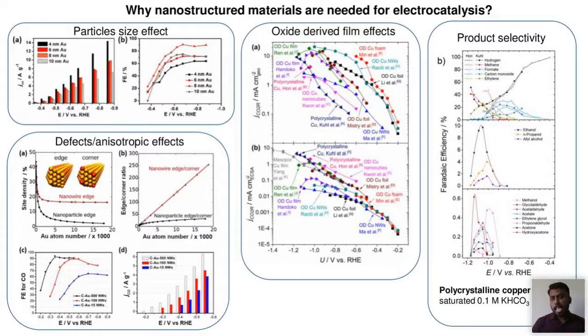So nanomaterial can be any shape, like a particle, sphere, octahedra, cube, or a nanowire, nanorod. So we basically classify the nanomaterial based on their anisotropy or their orientation, like zero-dimensional material, one-dimensional material, two-dimensional material, and 3D material. If you go for 3D material from zero-dimensional material, then you will have more pores in the structure. Because of the more available number of pores, the mass transport and electron transport will be much more efficient.